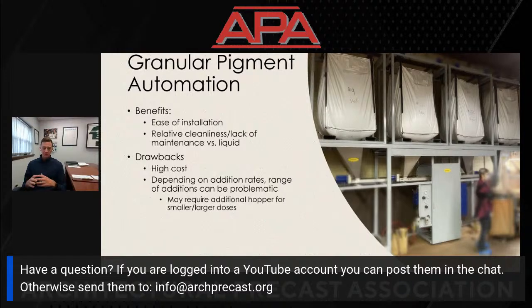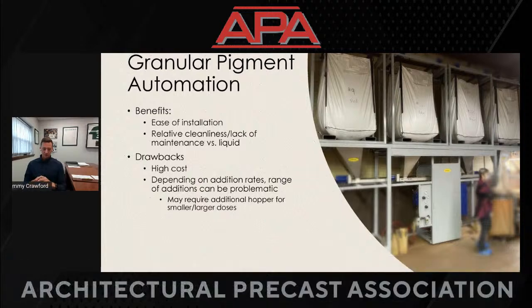And depending on the addition rate, the range of additions could be a problem. If you're using very high addition rates and very low addition rates, you may need a separate hopper, one for your smaller addition rates, one for your larger addition rates.